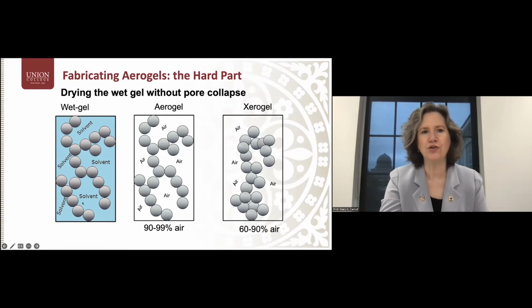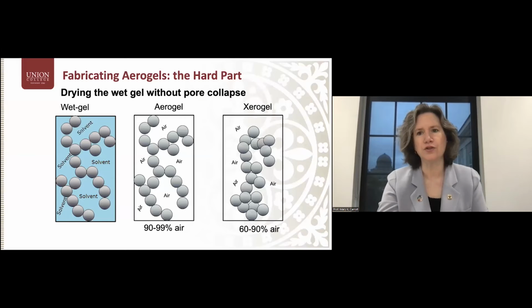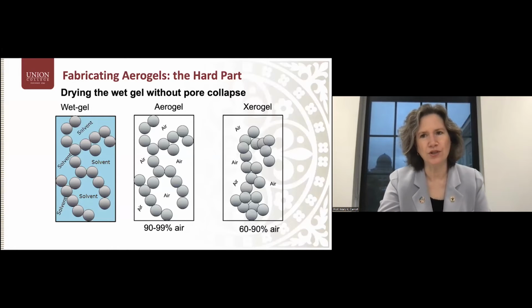So if we think about this cartoon of a wet gel here, we have formed colloidal particles. In this case, we're talking about silica particles, colloidal particles of silica. Those particles have connected together to make an overall solid matrix that extends throughout the container in which we've made this. And the pores of this material are filled with solvent, excess solvent from what we started with, because recipes typically involve starting with alcohols or an alcohol and water mixture in order to solubilize the alkoxy precursor, and also the solvent byproducts, which are typically the same solvents of the reaction.